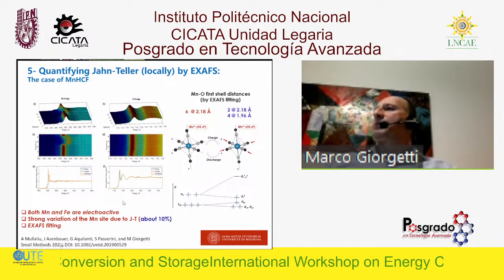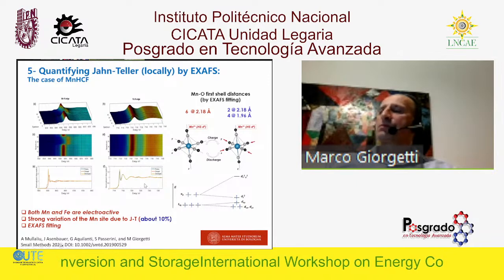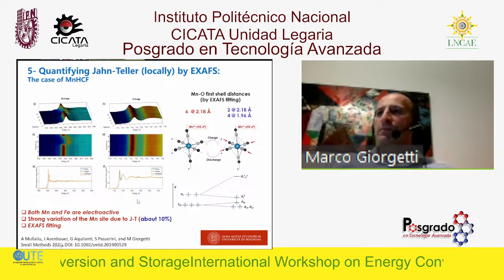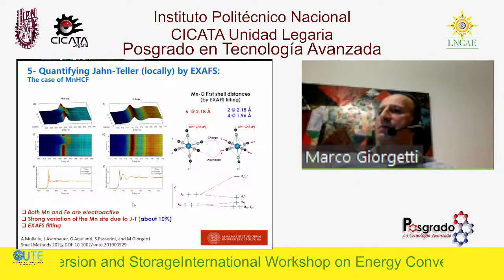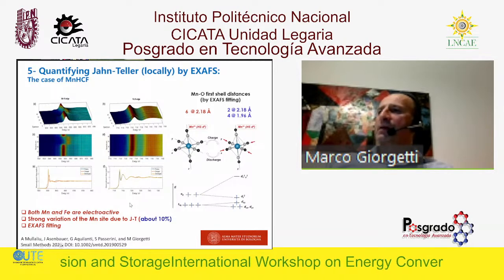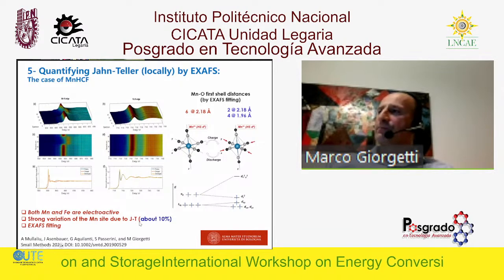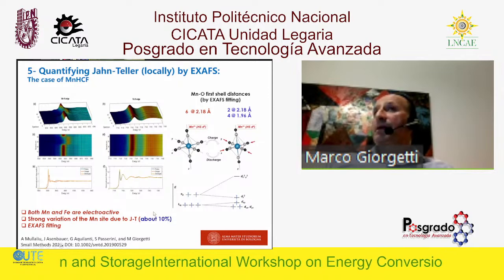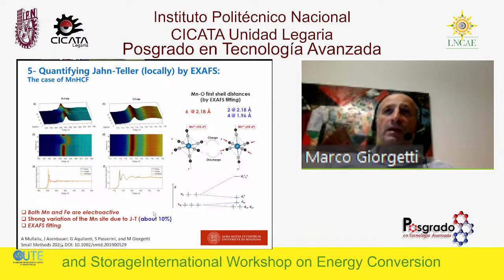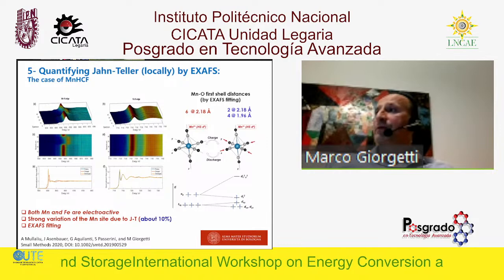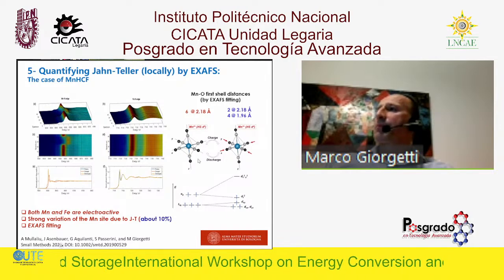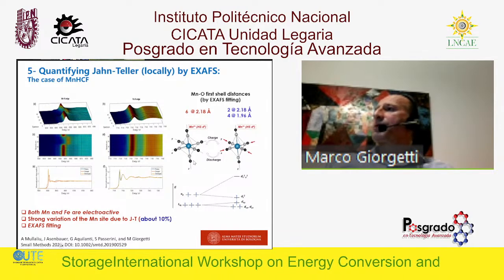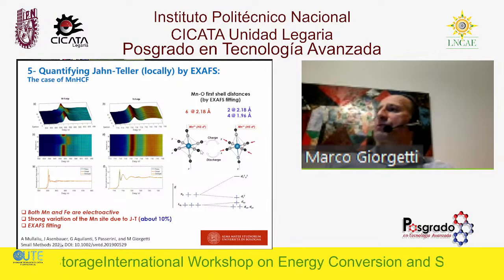But then, by EXAFS, we were able also to add a piece of information, because there was a strong variation on the manganese site due to Jahn-Teller. And we know that manganese 3+ is Jahn-Teller active, so it's something that could have been expected. Anyway, we were able to identify the local geometry changes.